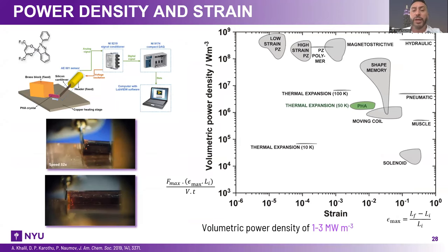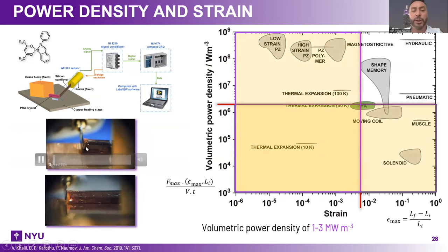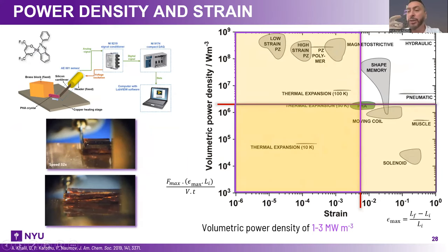One way that we wanted to characterize these crystals is to measure the force that they exert. And for this, we use very sensitive sensors that we put on top of the crystal as it expands, and we can measure the force. From there, you can calculate a bunch of other properties. And then we can put these in material science plots like this, and we can find out that, for example, this material is better in terms of strain than many of the other materials, and also better in terms of the volumetric power density, but it's not as good as some others. But keep in mind, what is important is we are here working with simple homogeneous crystals, unlike these other devices here, which are complex devices based on motors and, you know, different components.